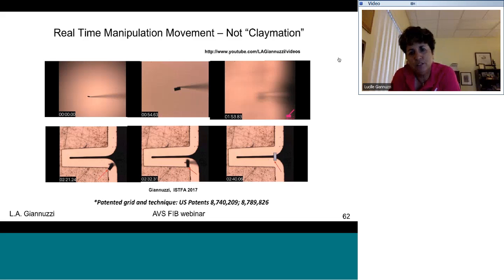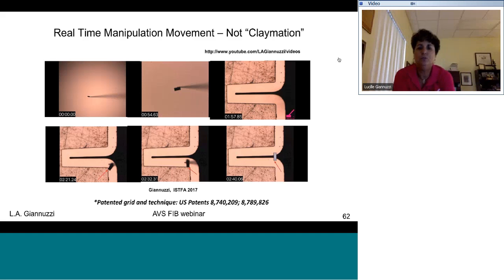Then you can use the grid itself to manipulate the sample and just orient the sample with respect to the probe in a preferred manner. So you can spin it around the probe, you can center it on the probe, and then you just slide the probe through the open slot, allowing the specimen to come to rest on the grid. And so that was just over about 2.5 minutes. So pretty easy to do.